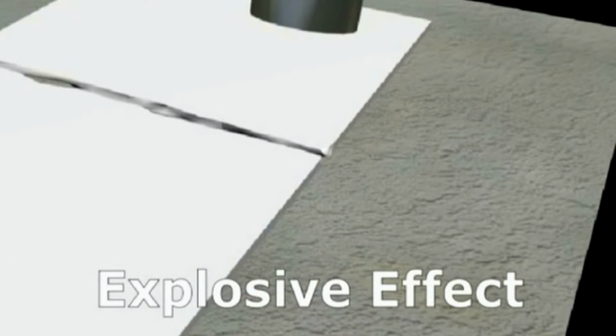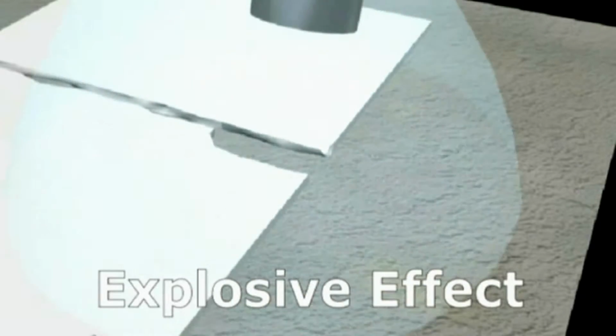Dry ice penetrates the coating and immediately transforms directly from the solid to vapor state. This results in a 700-fold increase in volume, an explosive effect that lifts the coating off the surface.